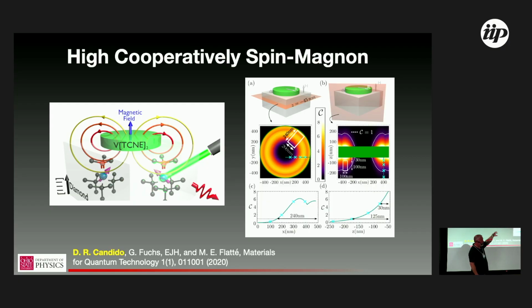And then Michael's question about the size scale of the quantization is, I would say, about 100 nanometers is when that starts to be interesting. So in the thickness modes, the films that I've been talking about are about 400 nanometers. So with disks in the microns range, you can start to get really substantial radial quantization out to 10 microns or more. You can use that as a perturbation, maybe for fine tuning. We haven't really pushed short range patterning yet. We just haven't had a reason to push hard on that. But I think that there's a lot of space for development there.